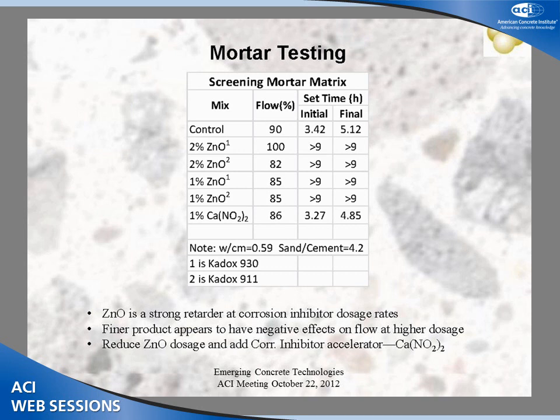Flow with the inclusion of the finer zinc oxide, the Kadox 911, was less than the control. And at a 1% zinc oxide content, the flow was not quite what it was with the control. And the mixture that had 1% calcium nitrite in it had a similar flow. But the thing that you really come away with from this data is to look on the right there at the set times. As you can see here, zinc oxide is a very powerful retarder of Portland cement.